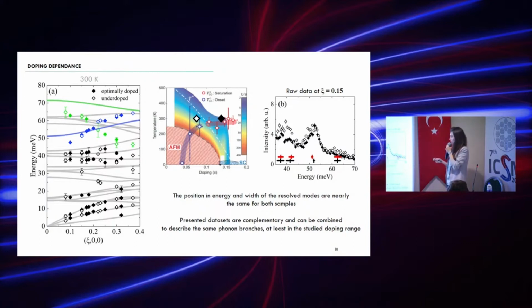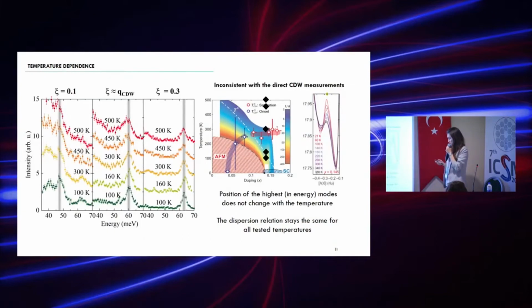But on the other hand, what we can say is that this anomalous anti-crossing is not really anomalous, it's just an internal property of the material. And to prove that, we also performed temperature-dependent studies. And so we go through these points across the phase diagram of NCCO. So we compared inelastic X-ray scattering data for different temperatures and at different wave vectors, close to the CDW wave vector and also at other points. And what we see is that the observed phonons are exactly at the same energy, at the same position. The only thing that is changing is the contribution from elastic lines, so the whole spectrum is going up here.